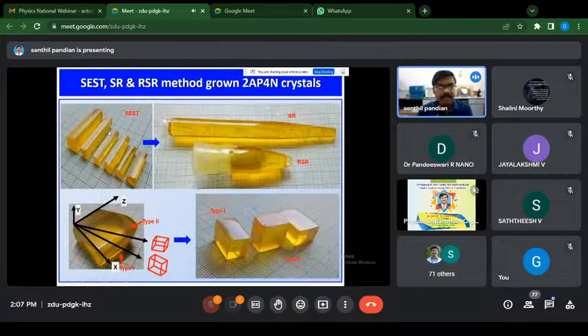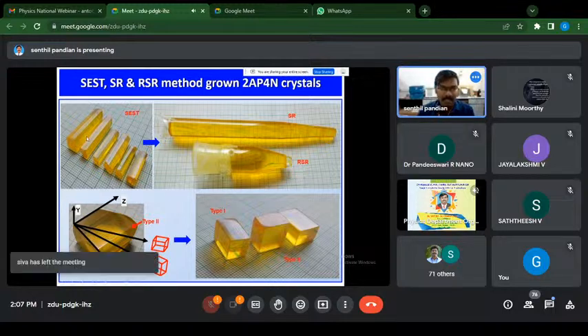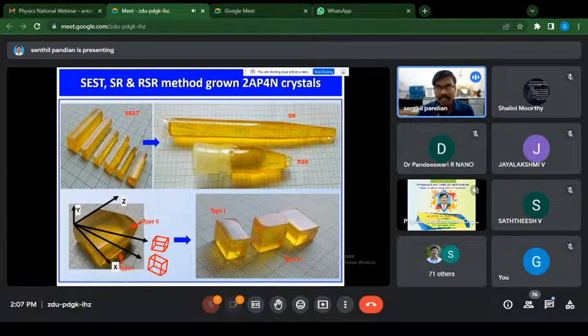So this is this 2AP4N, 4-nitrophenol derivative single crystal grown by the SEST. In a beaker, we have successfully grown this much of crystals by using SEST method for nonlinear optical application. The same crystal we have selected along its C direction, 001 direction, and we have mounted the seed crystal here, and we have successfully grown this much of large size single crystals by this SR method, Sankaranarayanan Ramasamy method.